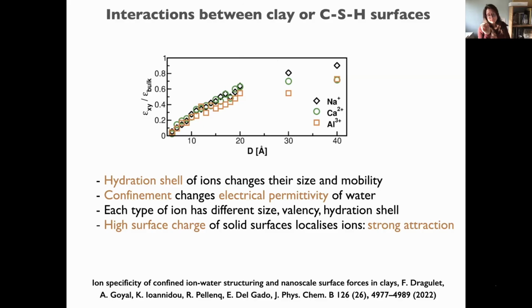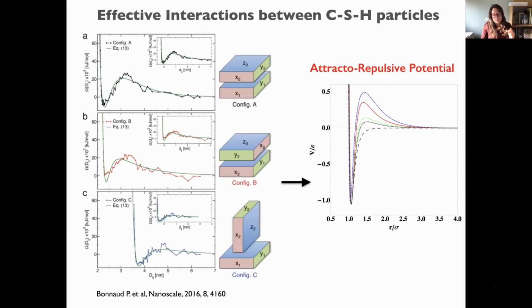It's the same way to see the thing: it's basically very immobile water stuck around the ions. It doesn't help screen the electrostatic charge, and we get very strong attractive forces between the CSH surfaces. So that was a parenthesis to understand more about the cohesion of cement.